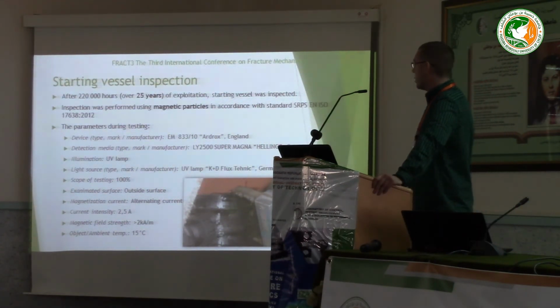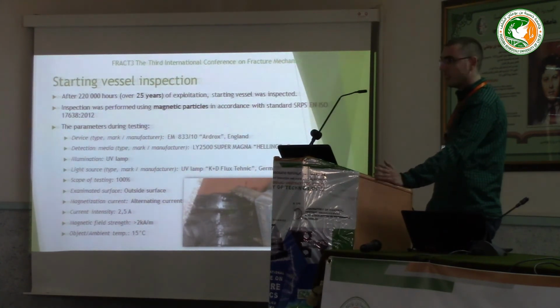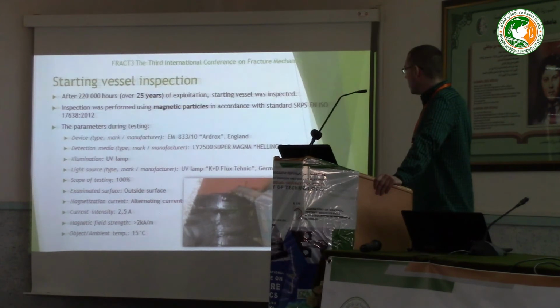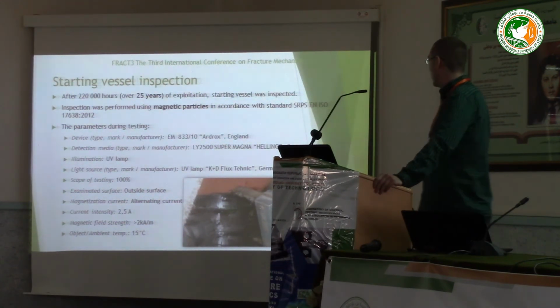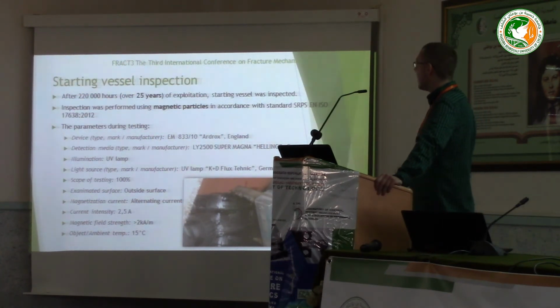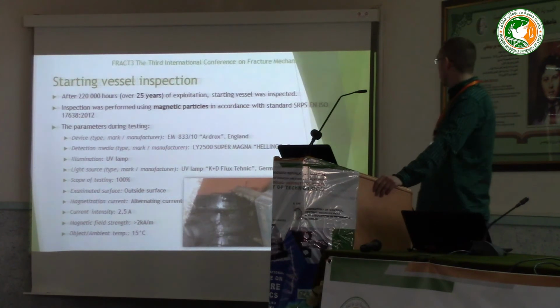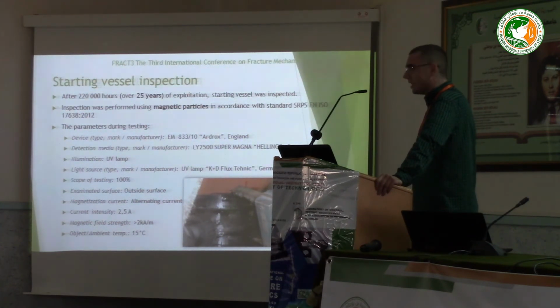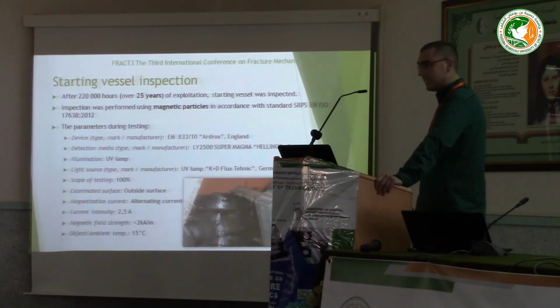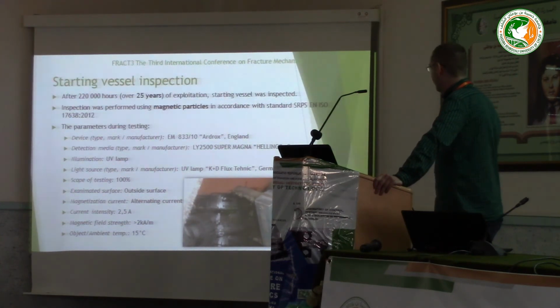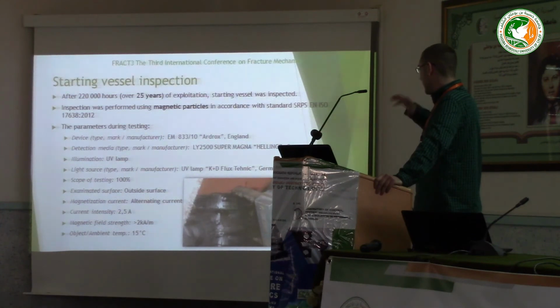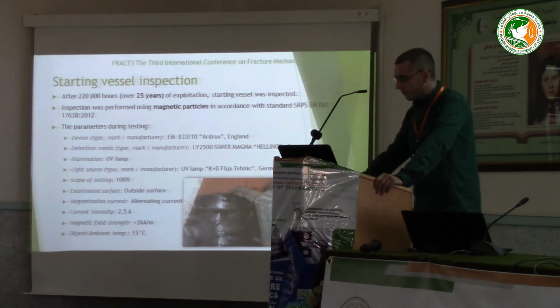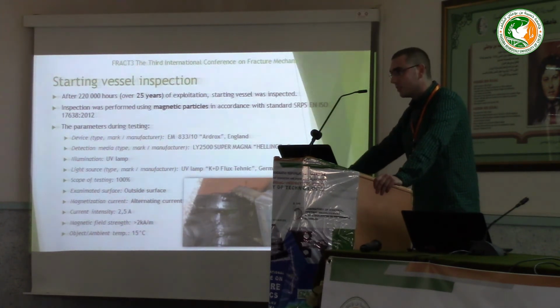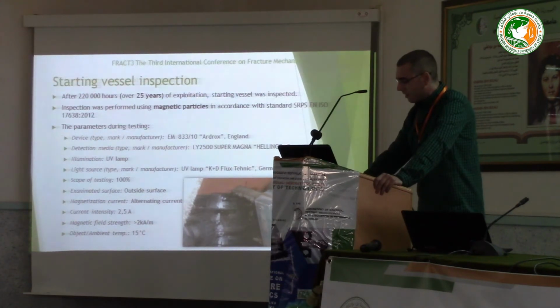And after the exploitation time, the starting vessel was inspected. The inspection was performed using the magnetic technique of examination in accordance with our Serbian standard, which is in accordance with the ISO standard. The parameters during testing or examination you can see on the slide. We used a device that is manufactured in England, and we examined the outer surface of the branches where the welds are done.